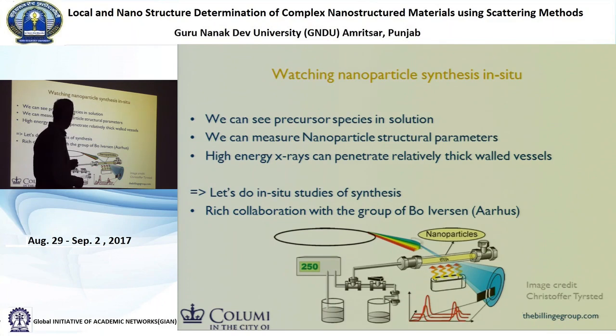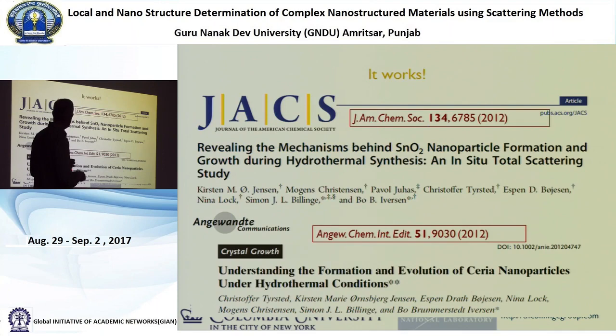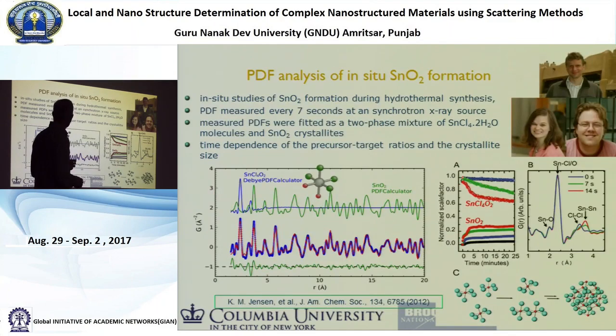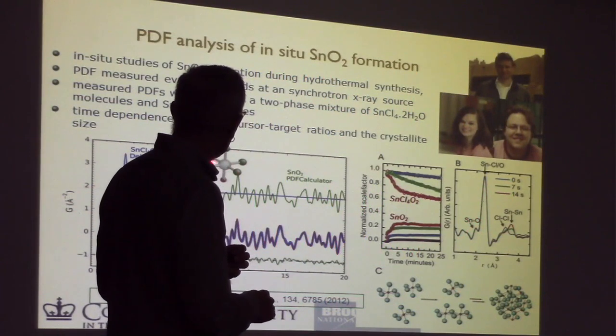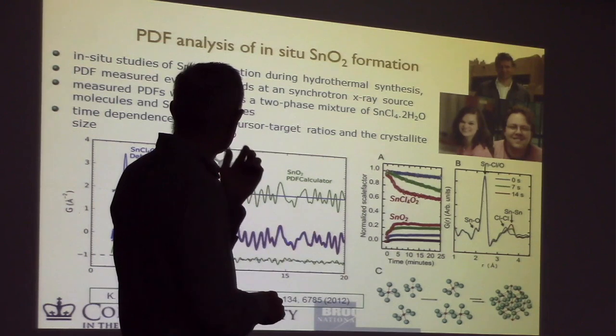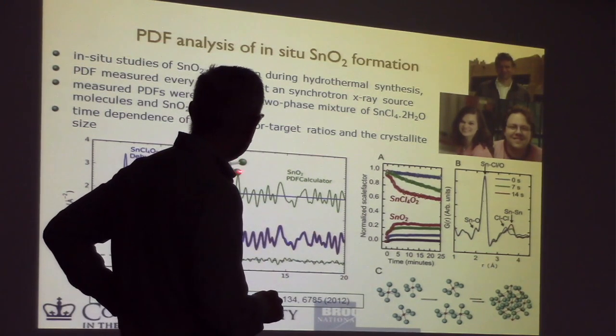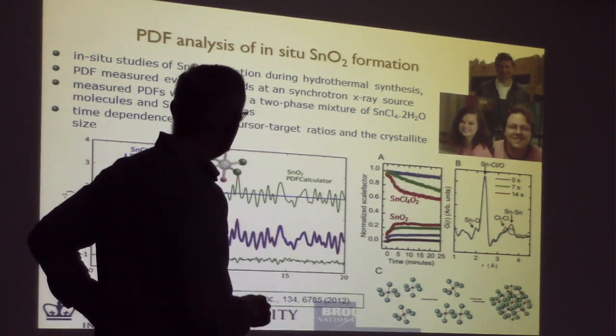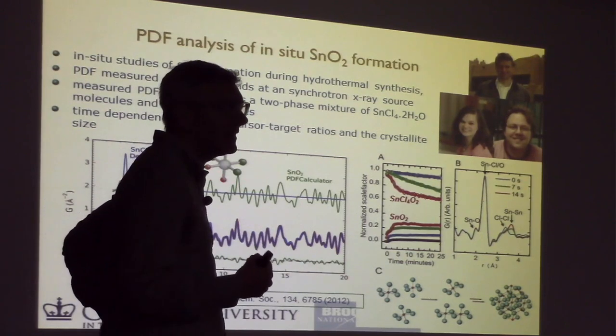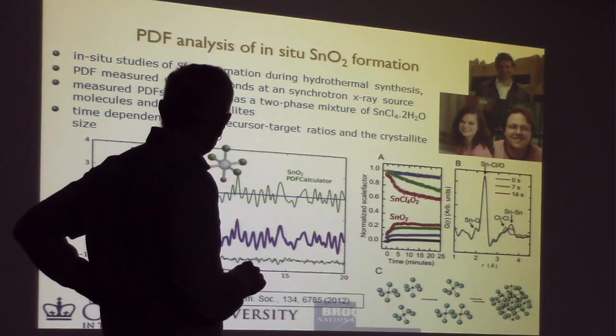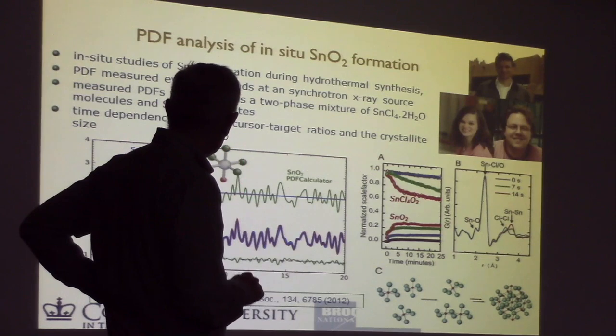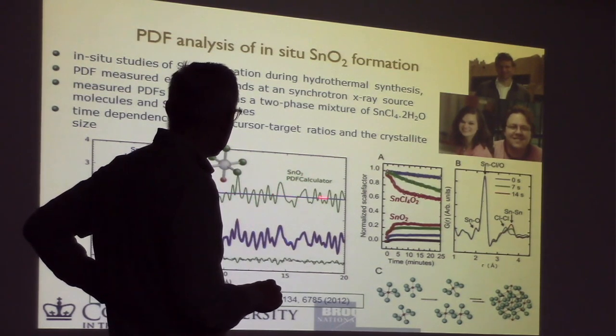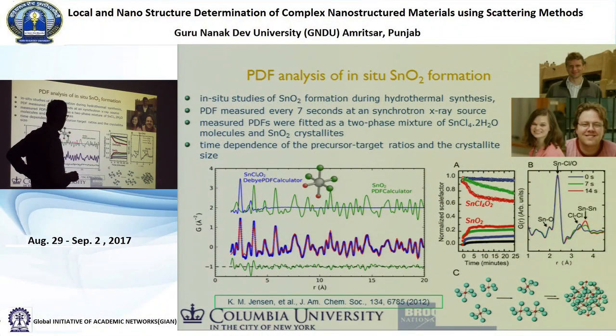So we put this reactor into the beam, and then we want to follow the synthesis. And we've done it on a number of different systems, tin oxide nanoparticles, cerium nanoparticles. In the case of the tin oxide, it was actually very interesting that the precursor looked like this. So it was basically tin, surrounded by four chlorines and two hydroxyl groups. So this is oxygen here. And it comes in different forms with either four chlorines or three chlorines. But we had to have a way of computing the PDF of this discrete object. And again, we needed to use our latest software to do that. But this blue curve is what this precursor PDF looks like. And the green curve is what the resulting tin oxide looks like. And what we can do is fit a two-phase model of just the tin oxide product and this precursor, and we get this kind of fit.